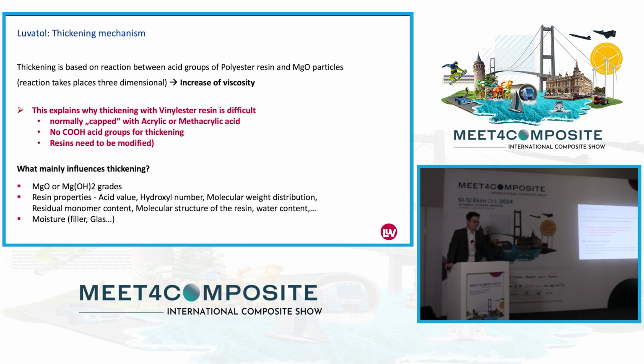There's one special case, and that's vinyl ester resins. It works. Normally, the vinyl ester resin is modified by the resin producers. I saw a few of them here, which probably know much more about modifying resins than I know. But normally, we recommend our customers to try it. So in this case, we use the most powerful MGO we have as a paste. We add it to the vinyl ester. And then we will check if it works. There are lots of things besides the formulation which influence the test and the usage of the MGO, which is, of course, the grade, which is the resin properties, moisture, and many more.